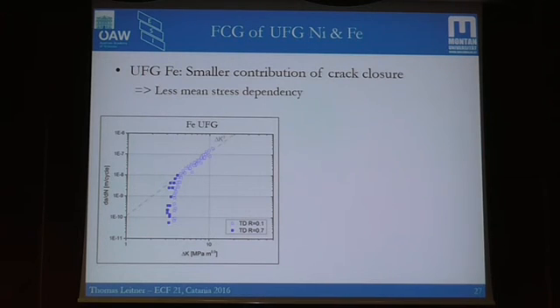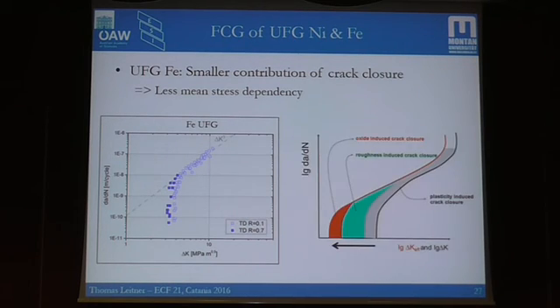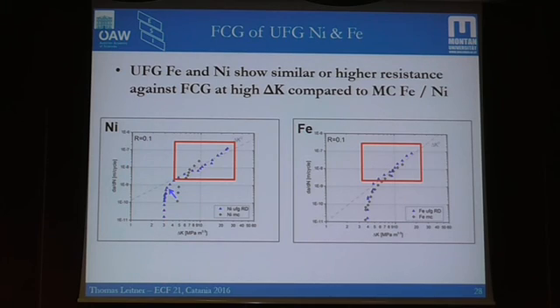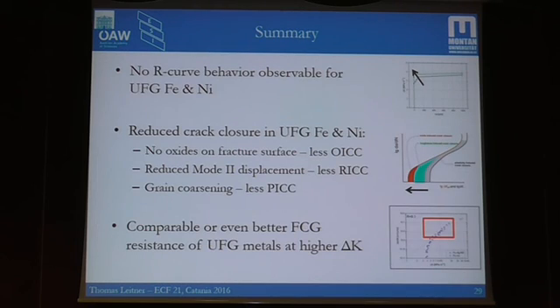So in ultrafine grained iron or ultrafine grained metals, we see a smaller contribution of crack closure, and therefore less mean stress dependency, because all these contributions seem to be reduced. So the fatigue crack growth of these ultrafine grained metals in the near threshold regime seems to be worse than their coarser grained counterparts. However, when we have a look at higher delta K values, in this region here, we found that we can get similar or even higher resistance against fatigue crack growth. So basically, we have these problems in the near threshold regime, but at higher delta K, it's not that bad actually. Okay, with that, I will leave you with my summary, and thank you for your attention.